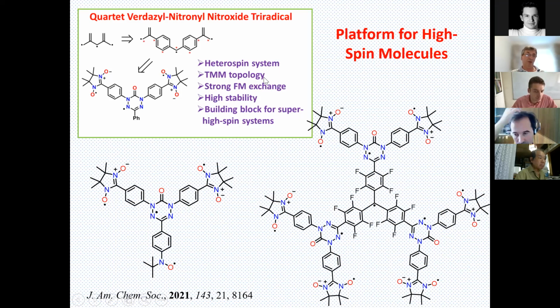So what is important, we succeeded in synthesis of heterospin systems containing oxo-verdazyl and nitronyl nitroxide building blocks. They have TMM topology. We observe strong ferromagnetic exchange interaction inside di- and triradicals. All of them have high stability. And what is more important, we have another phenyl ring, which can also be functionalized with a radical group to obtain molecules having an even higher amount of spin. So now we are close to preparing these tetraradicals, and planning an experiment as a synthetic path for preparing molecules having 10 spins.